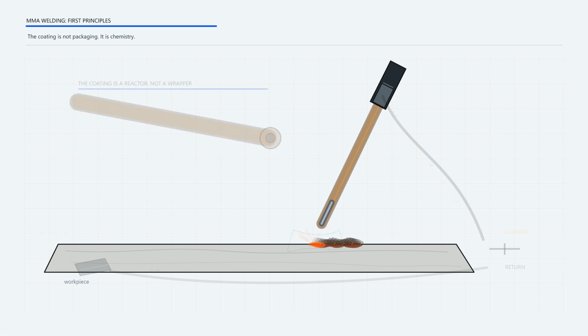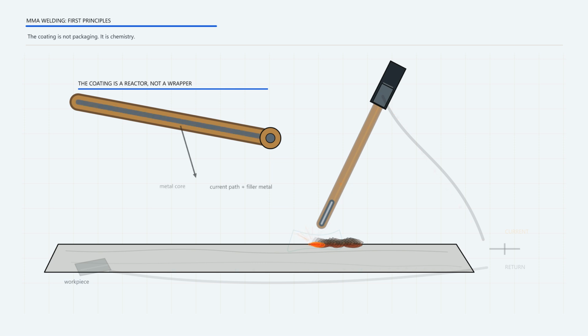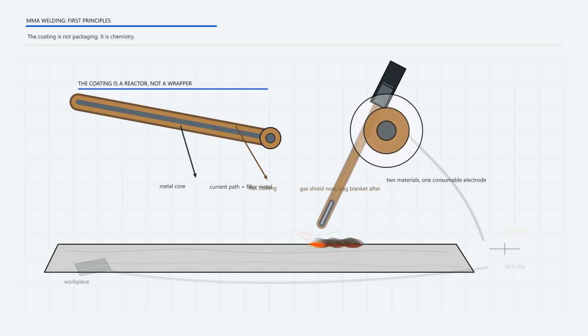In MIG, wire and external shielding gas are delivered as separate flows. In TIG, heat and filler are separated even further. In manual metal arc, the rod carries more of the system with it. Watch what happens at the tip. The arc melts the end of the metal core into droplets and into the weld pool. At the same time, the flux coating decomposes around that arc. The gas shield is short-lived and local. It protects the hottest metal right where oxygen and nitrogen would do the most damage.